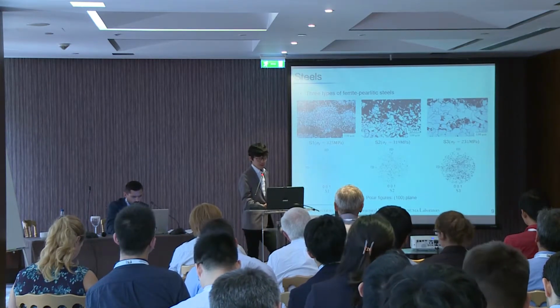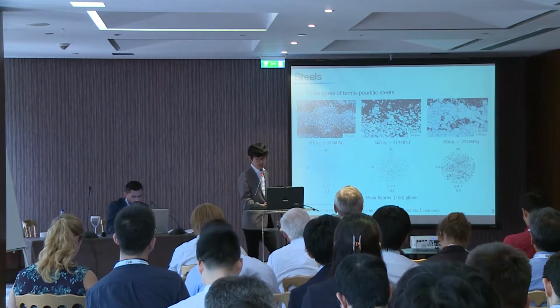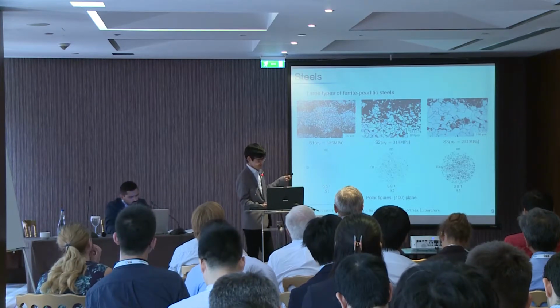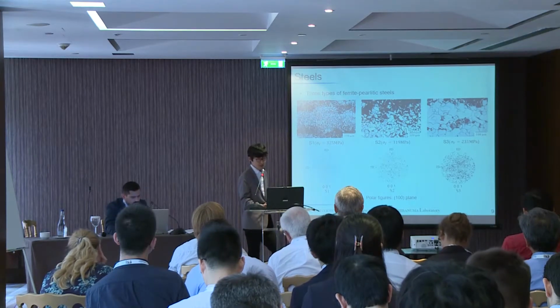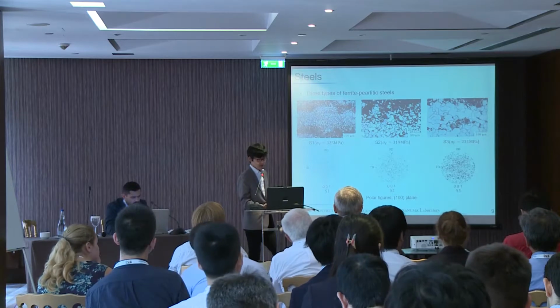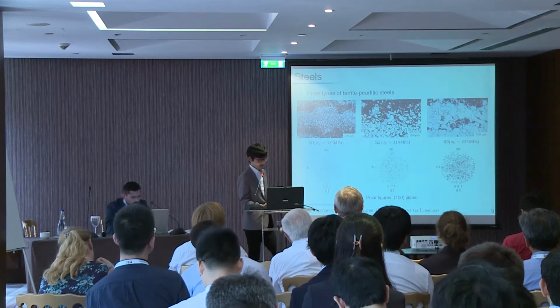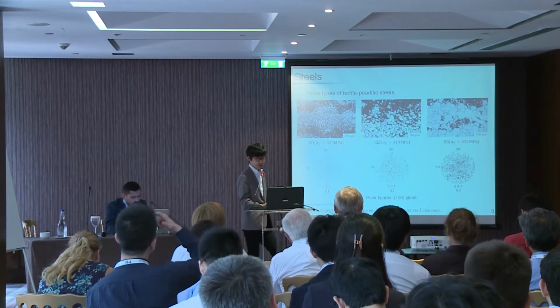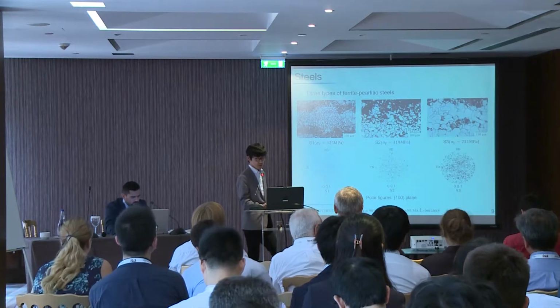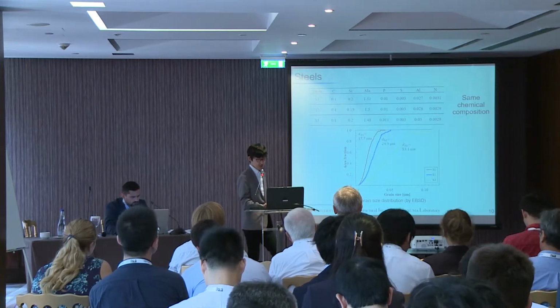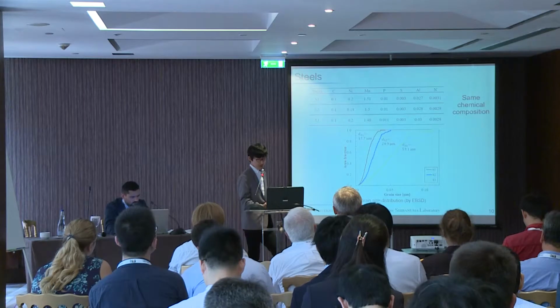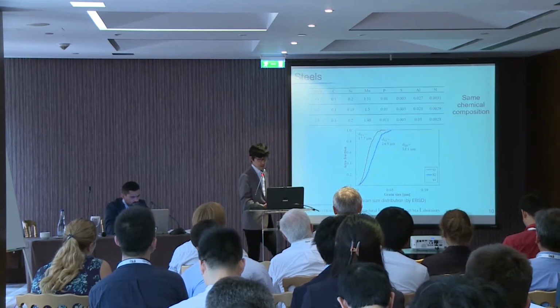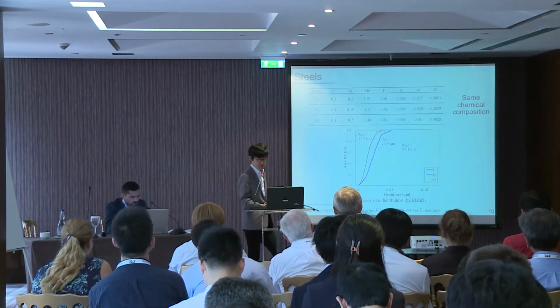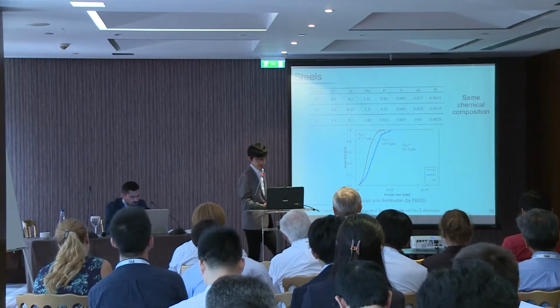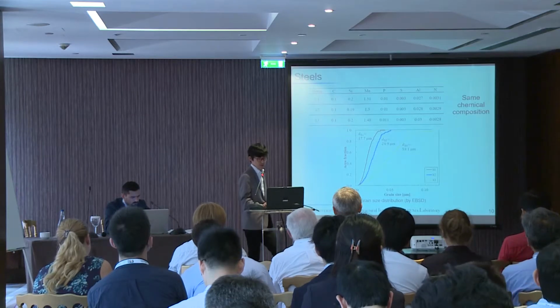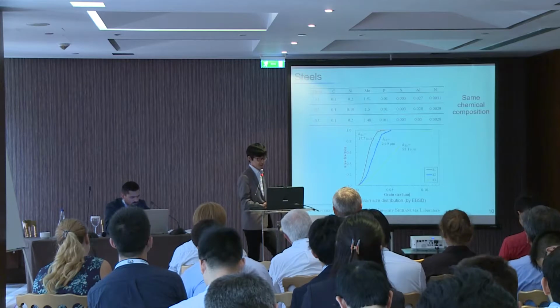We prepared three types of ferritic steels. The upper half is a picture of optical observation of microstructures of the steels. Sigma y is yield stress. And the lower half are the polar figures. As shown from these figures, these steels look isotropic. Chemical compositions are almost the same. From this grain size distribution by EBSD, average grain size is approximately from 15 to 55 micrometers. Grain size of S1 is the smallest, and that of S3 is the biggest.